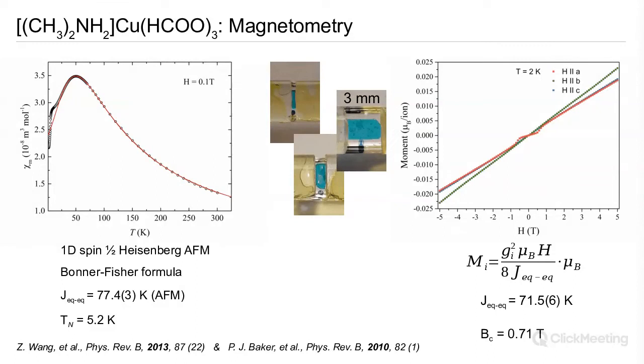What we see here is a linear dependence along B and along C. This is characteristic of an antiferromagnet, where the magnetization originates in essentially a field-induced spin canting of the antiferromagnet. This linear gradient is, if you like, a measure of the stiffness of the system, the strength of the exchange interaction that would rather the magnetic moments stayed anti-parallel.